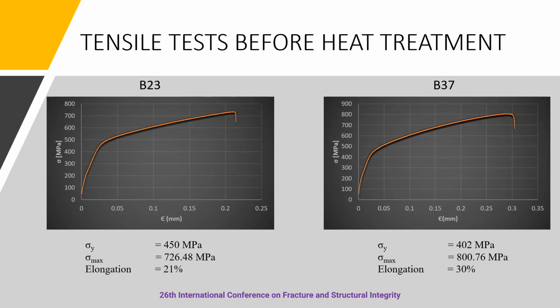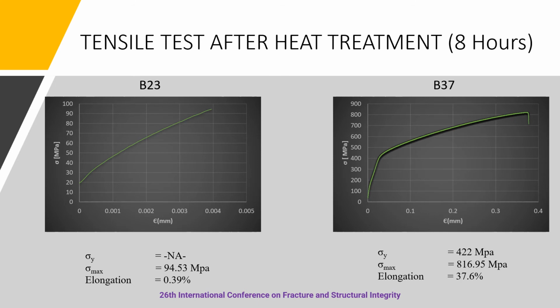In order to study the change in mechanical properties, both the alloys were subjected to a tensile test before and after heat treatment. This slide shows the tensile test results before heat treatment. It can be seen that for B23 the yield strength is 450 MPa, with ultimate strength and elongation being 726.4 MPa and 21% respectively. While for B37 the yield strength is 402 MPa, with ultimate strength and elongation being 800 MPa and 30% respectively. But after a heat treatment of 8 hours, things become more interesting.